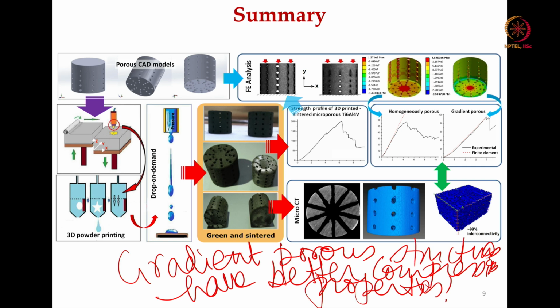So, in the last several slides, as part of this scientific case study, what you have learned is how to design simple solid cylindrical structures with uniform or gradient porosity using SolidWorks as a computational platform. Then how to do finite element analysis by constraining one end of the cylinder, applying the load on the other end, and introducing a concentrated mesh around the pores so that you can capture realistic distribution of the stresses. And from there you can also see how the strength profile can be predicted in case of the homogeneously porous and gradiently porous structures.